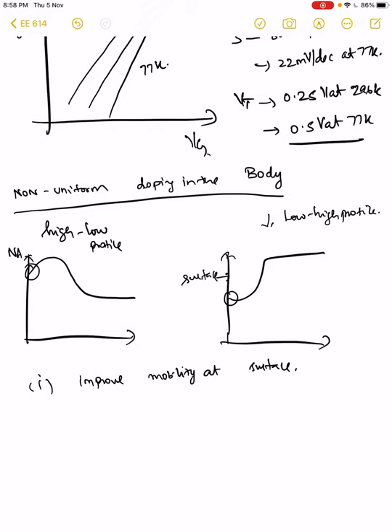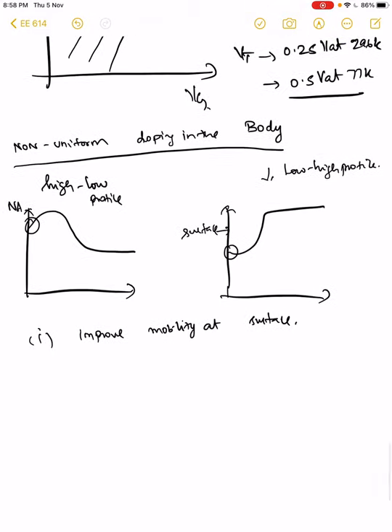That's one thing. The second thing is that it also reduces the transverse field. Why? Because any of the ionized densities you have here will lead to some charge densities at or close to the surface. So you have some depletion width here, or an enhanced depletion width here. This will lead to an additional electric field, EY, that is the transverse electric field, in addition to the longitudinal electric field that is typically applied between source and drain. So lower doping density here will lead to lower transverse fields and also a lower threshold voltage.